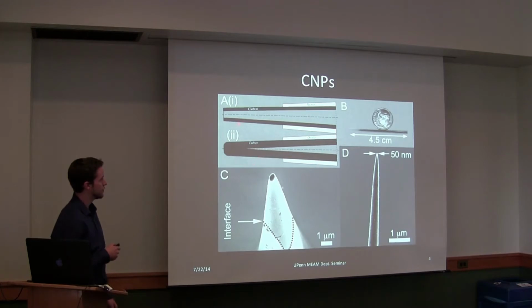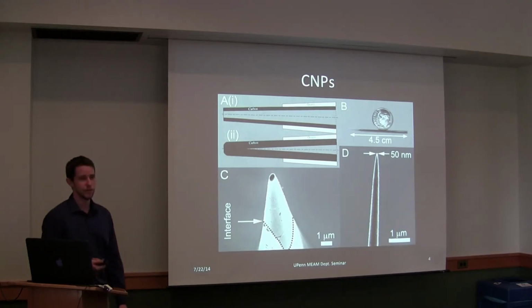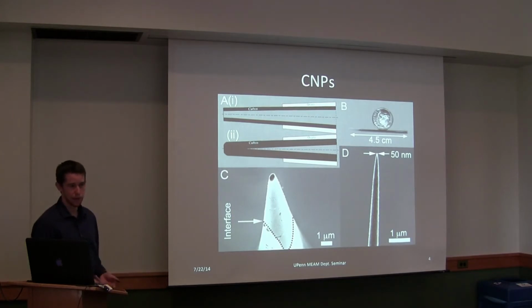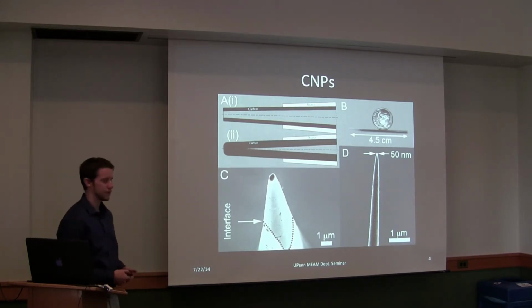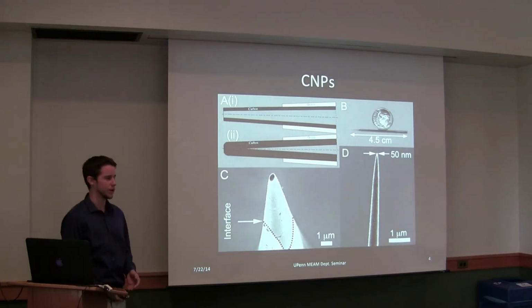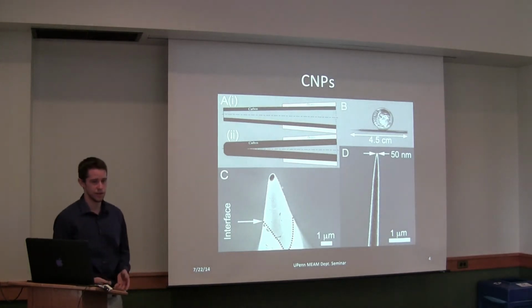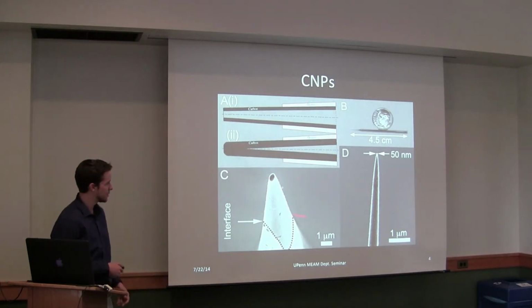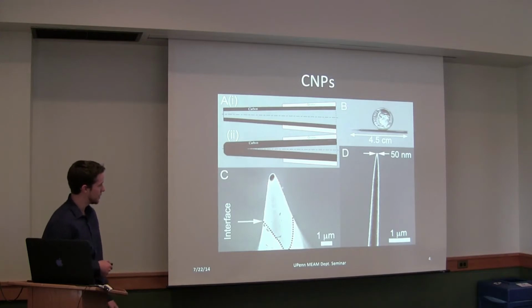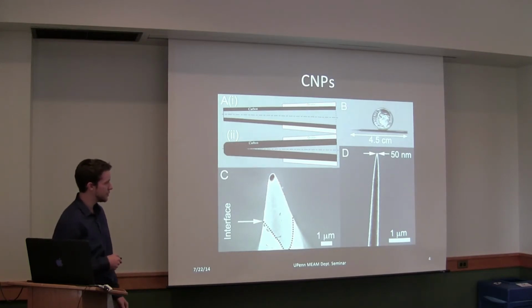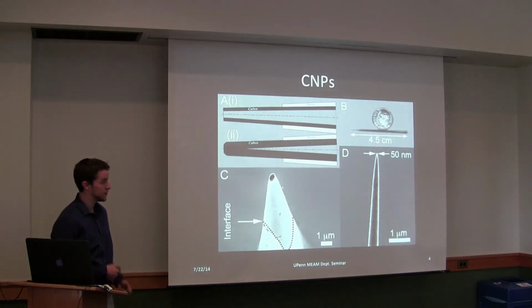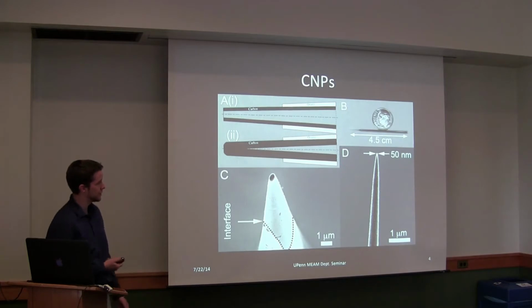We also have a continuous carbon layer from the distal end to the nanoscopic tip. And carbon is biocompatible, it's very strong, and it's also electrically conductive, meaning we can use carbon as a working electrode for electrochemical studies. Here are a couple SEM images showing both a hollow CNP, where the tip is still left open, and then we can also create these solid CNP tips with tip sizes ranging down to the nanoscale.